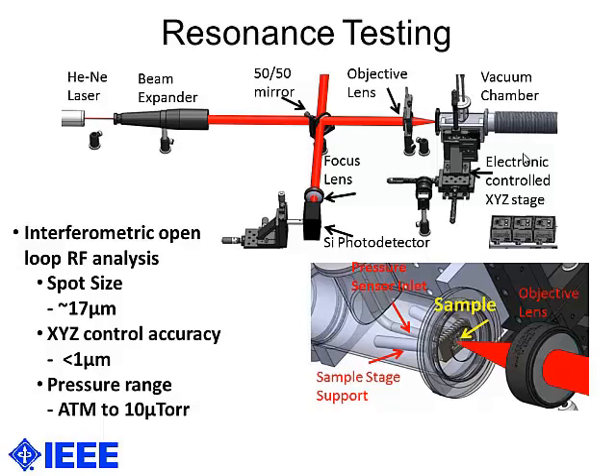Our sample is mounted to a DIP package, and a piezoelectric crystal is mounted below the membrane. The laser is then focused using the XYZ stage on the surface of the diamond membrane. We also sample the pressure as close to the sample as we possibly can. The separation between the pressure inlet and the sample is just a couple of millimeters.